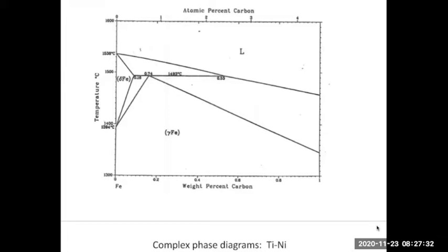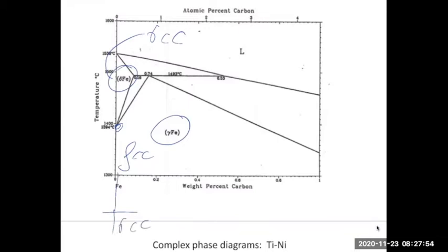Another interesting example is iron, and I've only shown the high temperature part here of iron, right? Because gamma iron, this is the iron carbon phase diagram, by the way, but gamma iron is FCC and delta iron is BCC. And again, this is a transition here that is vibrational entropy driven. The strange thing about iron, of course, for those of you familiar, is that if you go way down here, somewhere below here is again BCC. So that seems to violate my principle here.